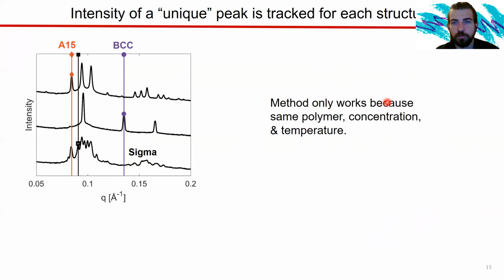Now, this method only works where you're tracking one peak at one Q position, because we're not changing the polymer, the concentration, or the temperature. So we know that we can look for a peak here, and if there's a peak there, it's probably just an A15 phase, or at least partially an A15 phase.